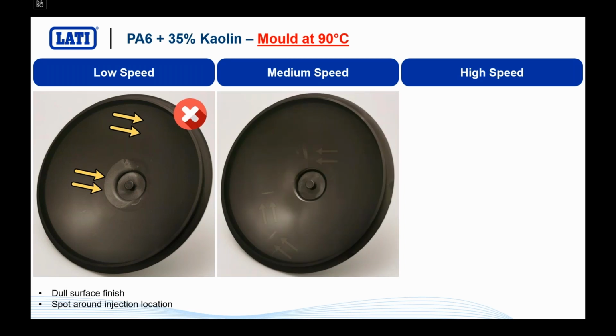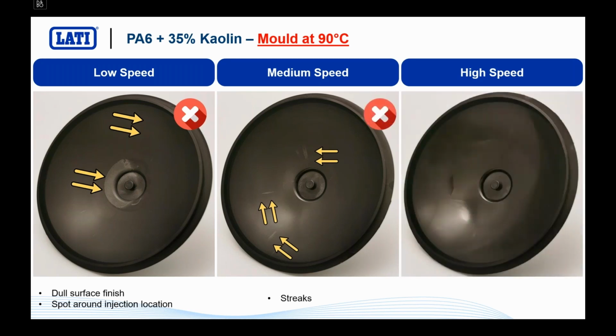You see an improvement here. You can still see some streaks here and there, some kind of stains here and there, but the situation will be, I would say, acceptable. It's not perfect, but it is absolutely acceptable when it comes to high speed and high temperature. So remember that to properly work on the surface finish of your part, you can work with the mold temperature as well as the injection speed. So in this very case, we wanted to play a little bit with the tool temperature, and it is evident how it was possible to improve the surface finish even of the worst guy of all, which is kaolin.